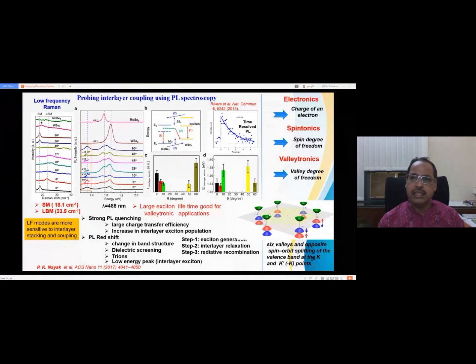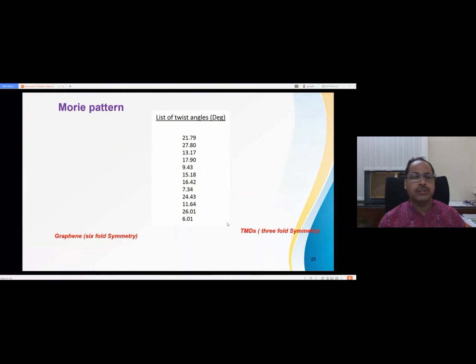And this lifetime, if you measure, this is a Nature Communications paper. It was predicted that this Valley lifetime is of the order of nanoseconds, whereas the intralayer exciton lifetime is picoseconds. Due to the large Valley lifetime, it is good for Valleytronics applications. Now, Professor Xiaodong Xu at University of Washington is mostly working on this Valleytronics material. You can get very highly cited papers from him.